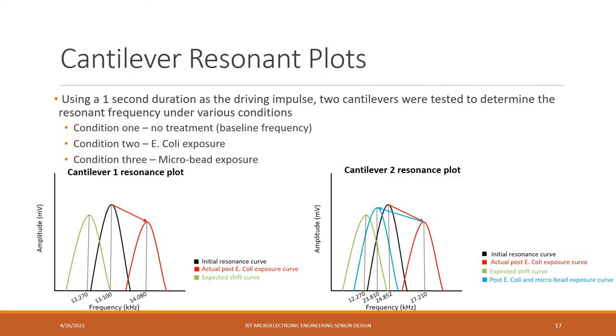The two cantilevers were tested with the presence of E. coli and without the presence of E. coli. Both cantilevers showed an increased resonant frequency after the E. coli was dispensed. The likely cause of this is the fact that the crystal-like formations of the E. coli stiffened the cantilever, leading to a higher spring constant. To verify that a mass will decrease the frequency, 500 nanoliters of a microbead solution — 10 micron diameter silica beads — was dispensed on the cantilever surface. Once dried, that cantilever was tested again. We moved from a black peak to a red peak due to the higher spring constant caused by the salt crystal E. coli film, and then down to a blue peak, which is a lower frequency caused by the combination mass of E. coli and the mass of the microbeads. The green curve represents what would be the expected frequency post E. coli exposure.